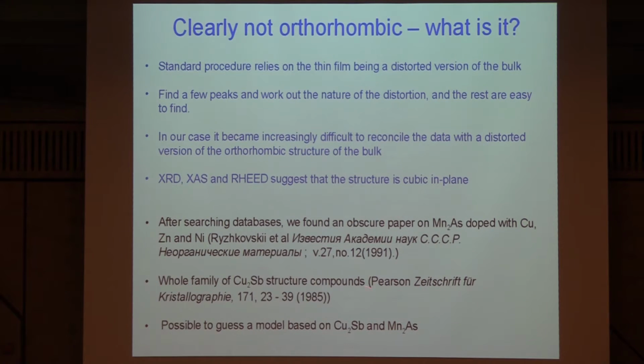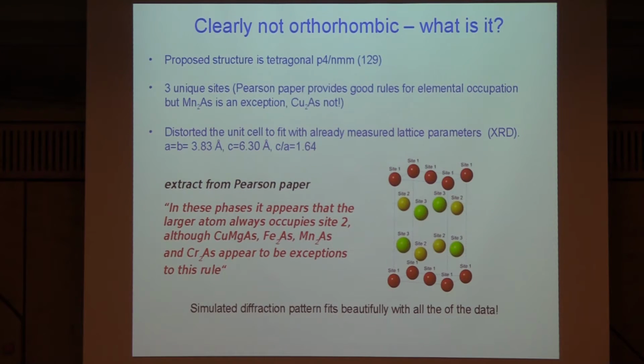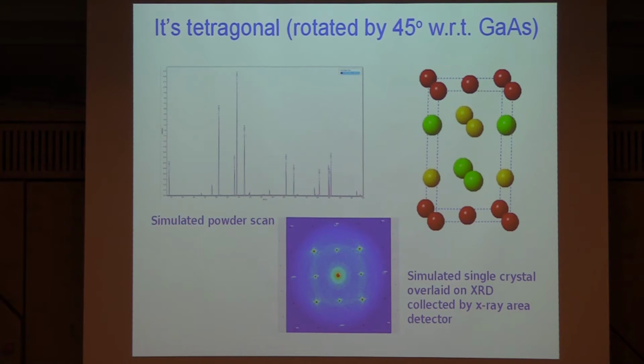He was able to guess a model based on the copper antimony structure. The other good thing about the Pearson paper was that we proposed this structure up here, but it also gave us some rules, or at least potential rules, for occupying the sites and saying which atom was going on which site. So not only did we have the structure, but we had some way of estimating the sites. We then simulated the diffraction pattern, as you might, and it fits absolutely beautifully. This is real data overlaid over the simulated pattern down here in this wide angle X-ray, and it's wonderful.